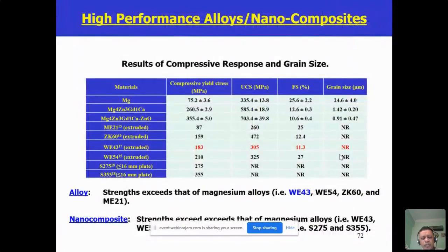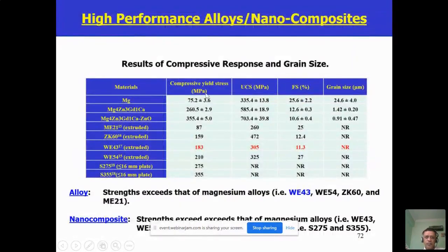We are also involved in the development of new magnesium based materials and of course the nanocomposite. And if you look at the second row here, we developed this material with 4 zinc, 3 gadolinium, and 1 calcium. And you see the properties are almost tripled in the compressive yield strength, and UCS is almost 1.5 times. Failure strain in this situation reduced to half, but remains more than 10%. And of course, the grain size reduced.